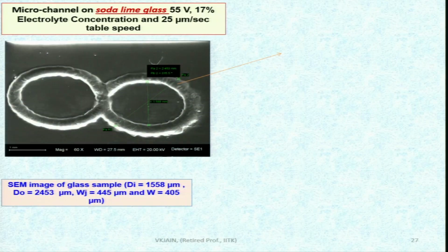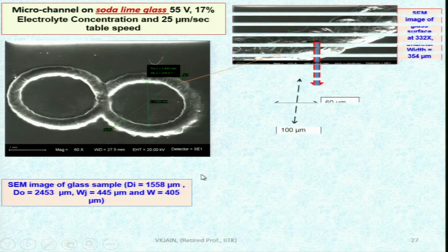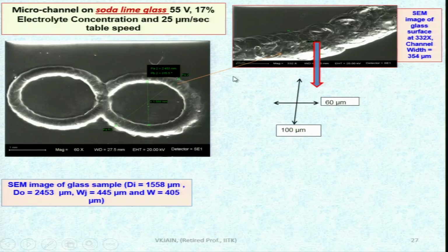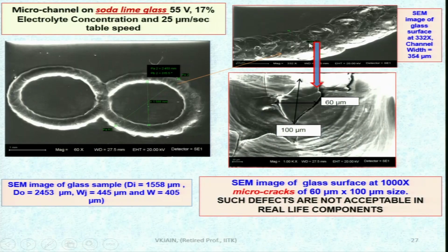Microchannel on soda lime glass. This I have shown you already. You can see the enlarged view of this. Now, this is what I want to show, that this is not so good, because this is the kind of surface you are going to obtain in real life, and which is not acceptable. It is the SEM image of the glass surface. If you further magnify this part, you will see there are micro nano fractures of the workpiece. Why I am showing it deliberately is that after seeing this, you have to optimize the machining parameters so that you do not get these kinds of defects on the machined features, otherwise it will not be acceptable to the user.